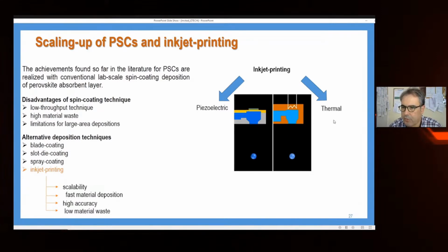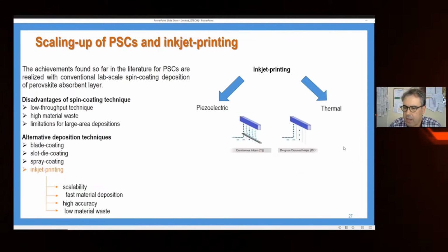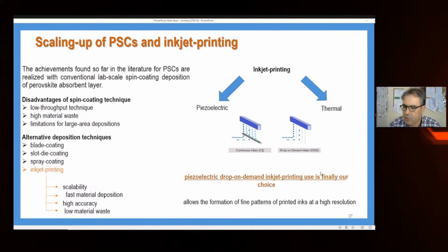Between the two technologies of inkjet printing, we followed the piezoelectric method, which means that from the printhead, we can see the drops coming out. Of course, there are two separate technologies in inkjet printing based on piezoelectric printheads. We followed the drop-on-demand inkjet printing method in our printers. That's why we get very good, high resolution, and finally, a very homogeneous film of perovskite.